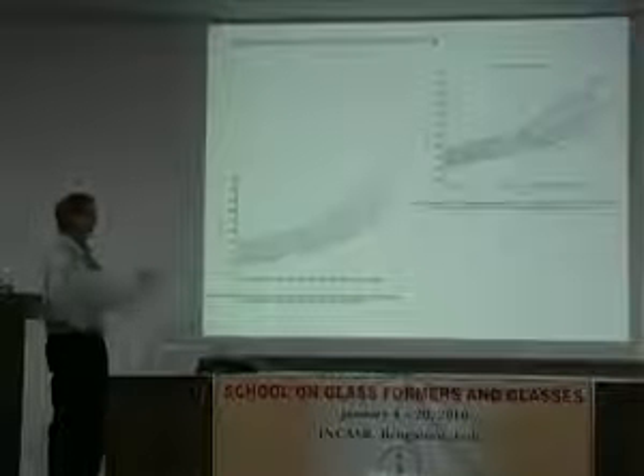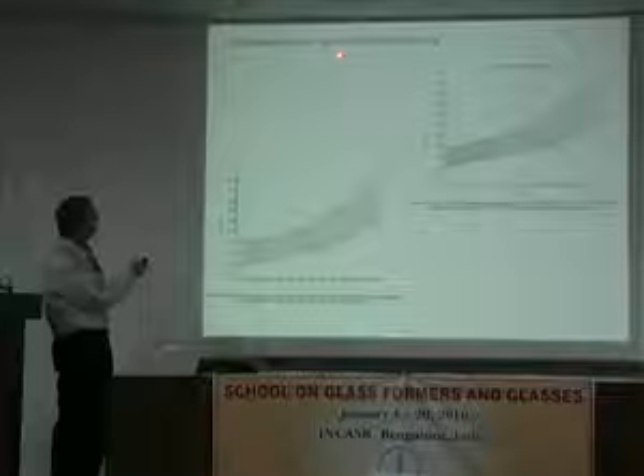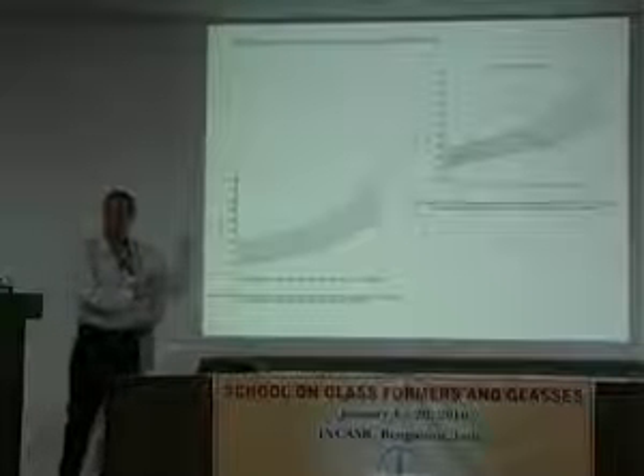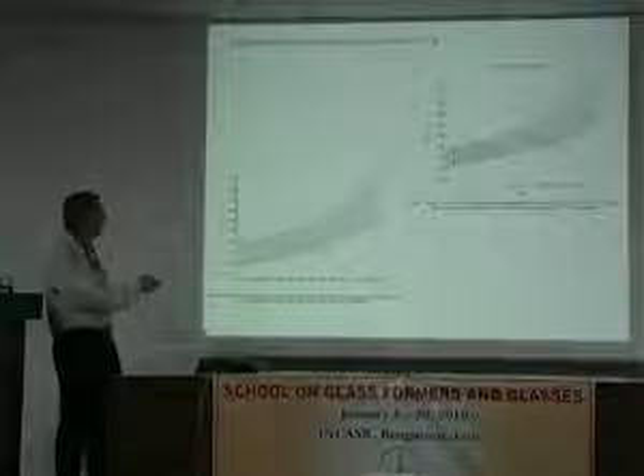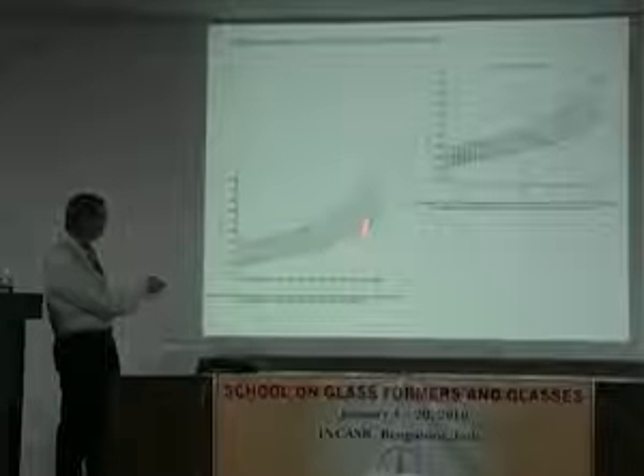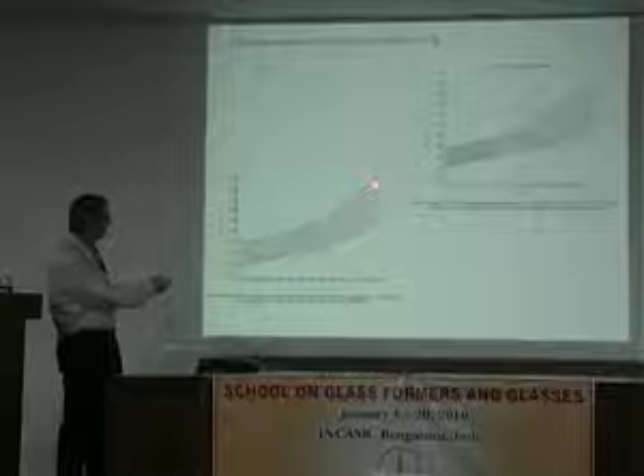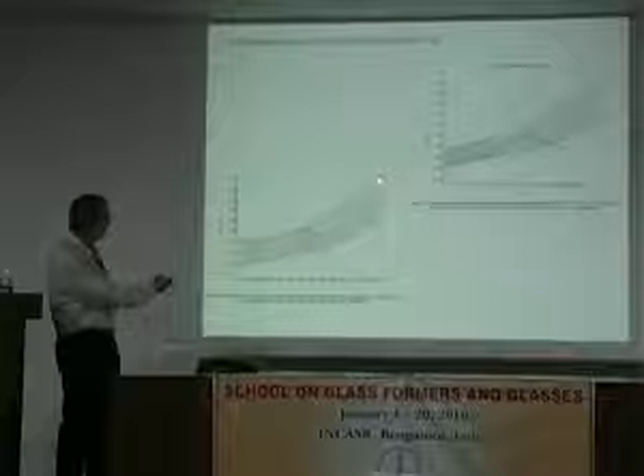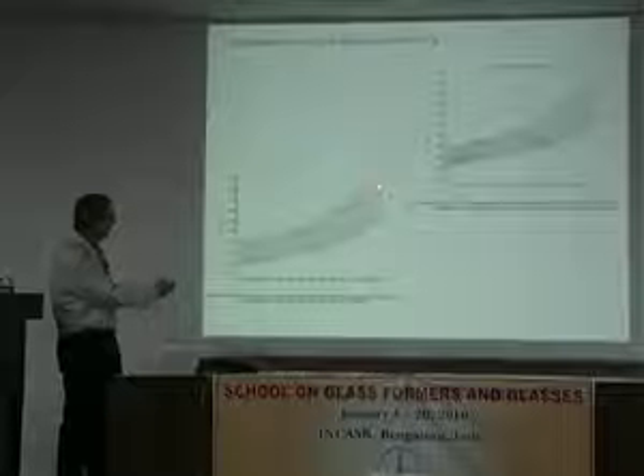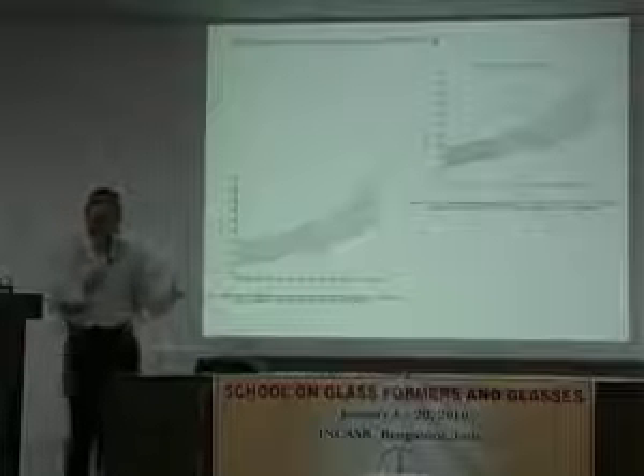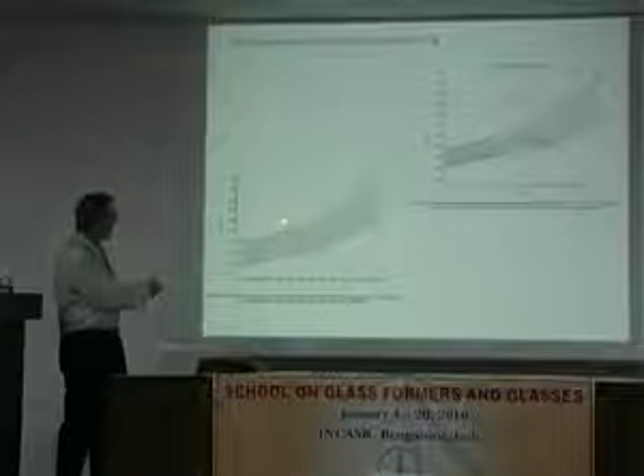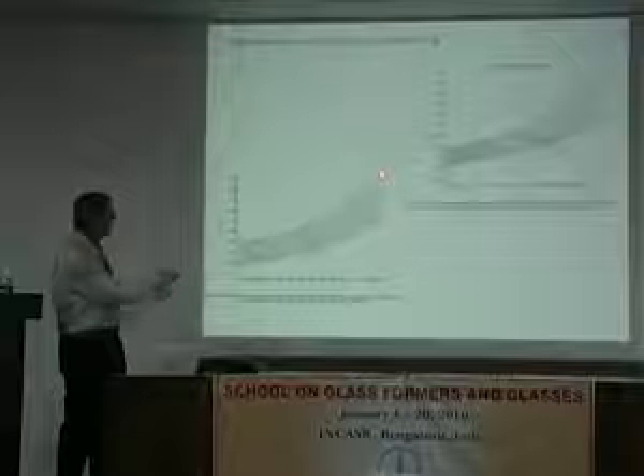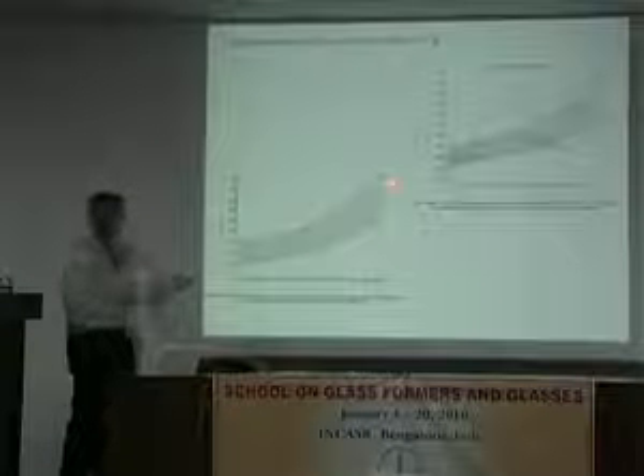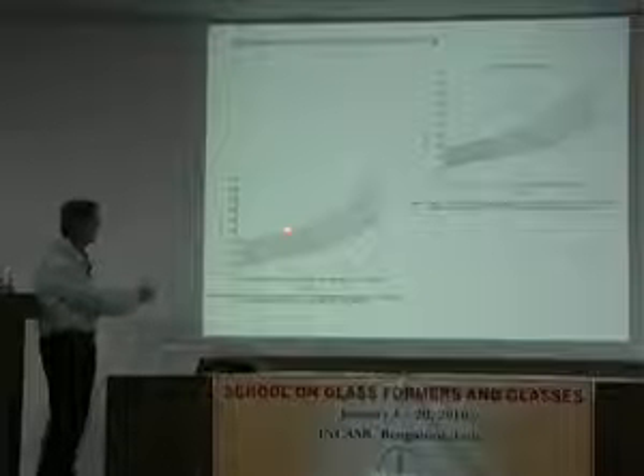Here's another example. This is from McKenna and Goldstein, and this shows the path dependence of Tg and the pressure effects on Tg. So, of course, Tg depends on pressure. We saw that. This is a more conventional type of experiment where what you do is you go into the liquid state, and then you change pressure. And so here, then you cool it and watch the glass formation at constant pressure. So that's an isobaric surface. And you can define your glass transition surface from this set of experiments. Of course, this is an equilibrium surface. This won't change with path. This is the glassy surface.